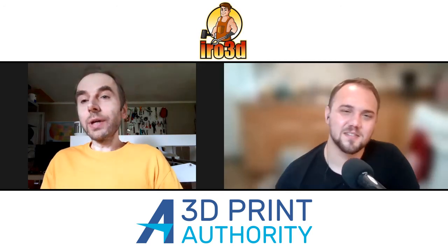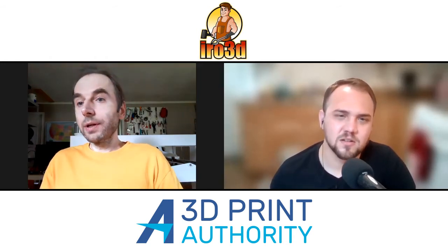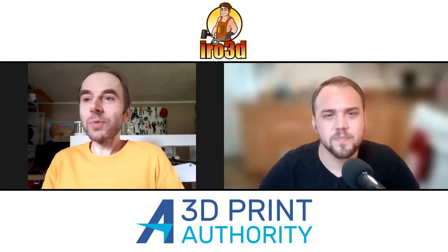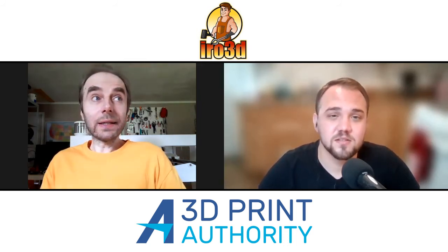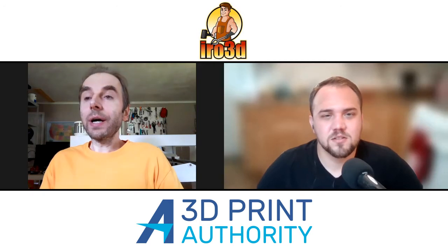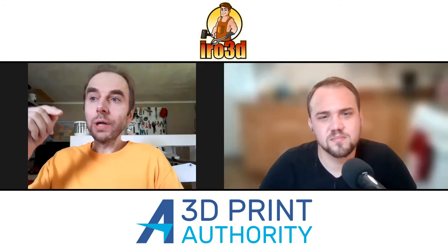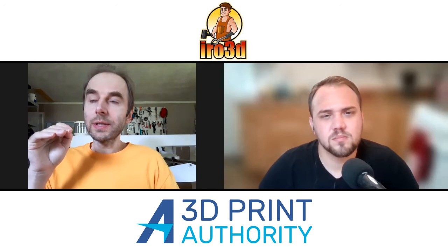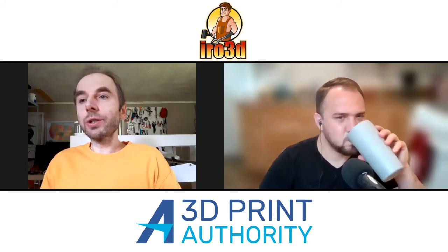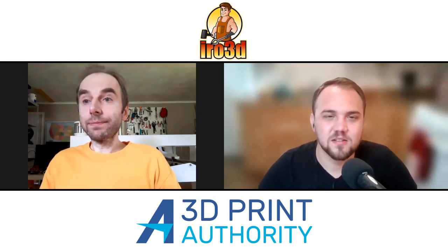If you want really high quality parts, it's better to use hydrogen instead of carbon, because hydrogen does not have this Boudouard reaction where it transfers between solid and gaseous. It's always gaseous, so it doesn't mess up the chemistry of the part. You might get some hydrogen absorbed into your print, but it's fairly easy to get it out. On the way down, when you cool the part, you wait a couple hours at something like 300 degrees and the hydrogen gets out. You can read about hydrogen embrittlement. So basically, hydrogen is much better in theory.